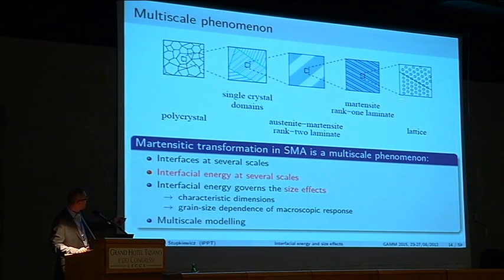But if we also look at this picture from another perspective, we see that we have interfaces everywhere. Microstructure means we have interfaces, and so we have to consider these interfaces on the microstructures which evolve, which change, which brings additional complexity, but it also brings us some beauty, because this is exactly what we will be looking at, because each interface carries some interfacial energy, and I will elaborate more on that. And then, as we will see, interfacial energy and the balance of different contributions governs size effects, so that if you consider these issues, you can try to predict characteristic dimensions of the microstructure, grain size dependence of the macroscopic response, or things like that.